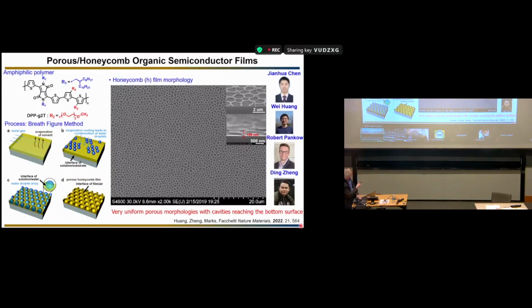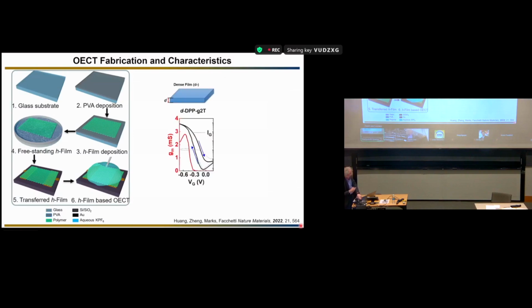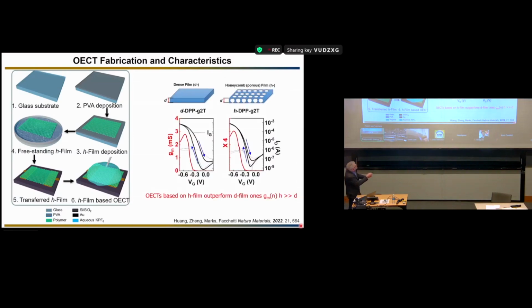So I can create this film, and then I can spin coat the same polymer in dry conditions, the relative humidity used in a fab, 50%, 45%, and you have a dense film. So we can make devices based on the dense film and the porous film of the same polymer. And what we see here, let me skip the fabrication, are the transconductance, current, voltage responses. This is for the dense film, and for the honeycomb, this porous film, the current is about 4 times larger, so it means we can accumulate more carriers per unit volume of the polymer.